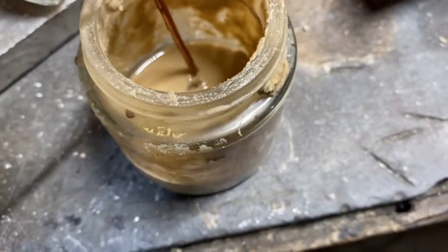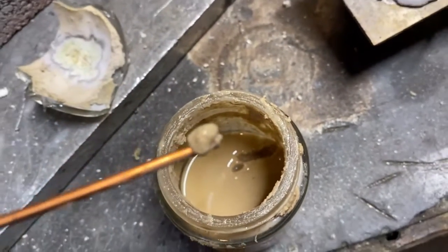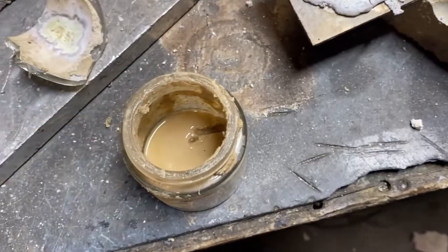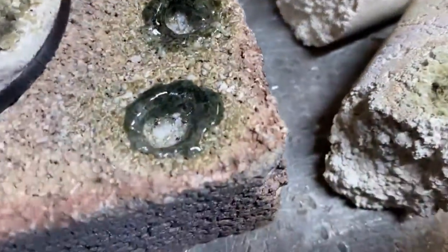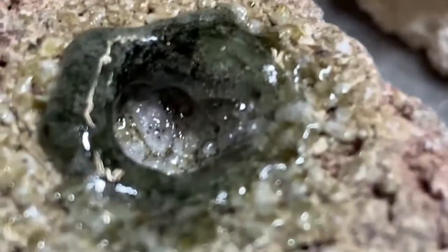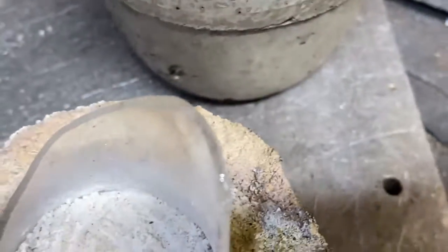This amount of gas we're throwing into this little torch — here is the glue, and I made this a long time ago. It's still somewhat pliable. This stuff is a viable product right here, a nice little heat shield. I mean, I don't think it's going to last forever, but it outdoes fire brick, doesn't it? Look at the holes — I don't know if the camera's picking up the depth of how deep these holes actually are. You could drive a car through that. And these here suffered no such response — of course they're not as porous, they're denser. Look at that — didn't do anything. This thing just laughed at it.